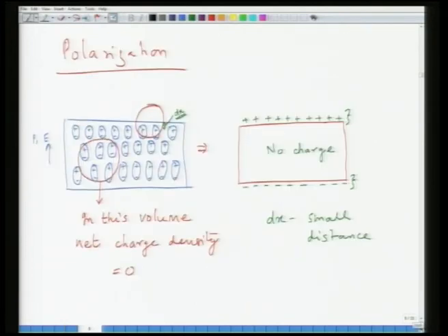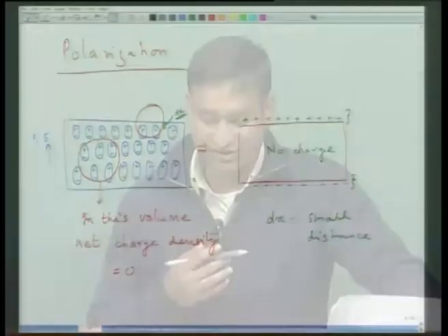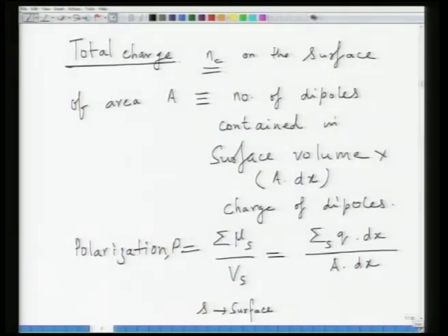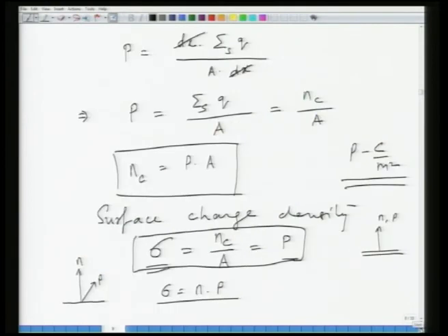So then we looked into what is the origin of polarization. For that we drew a schematic picture. We took a dielectric material and assumed that this dielectric material is polarized. Under the polarized condition, we probed two volumes. We can probe inside the material itself. If we probe inside the material itself, we find that the net surface charge density within that particular volume is equal to 0, because positive and negative charges cancel each other. However, when you probe at the surface, what you find is that the surface has a particular type of charge in excess, and this excess charge gives rise to a build up of charges on the surface. Because of the application of an electric field, and the creation of dipole moment, these charges are shifted by a small distance, let us call it dx. So from this, what we worked out was the concept of polarization, which is nothing but your surface charge density, as we found out later on. So this sigma surface charge density is nothing but your polarization.